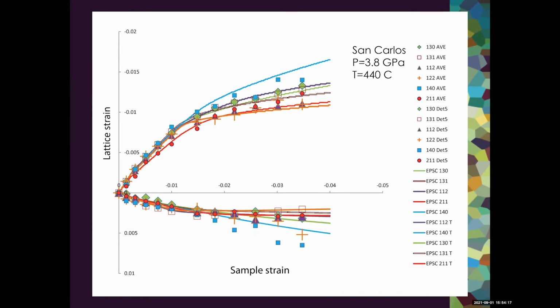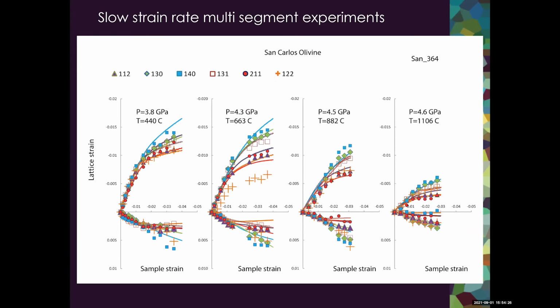Then as we add in the slip systems of olivine and kink banding, we're now able to get those curves to flatten out and overlay the data much nicer. So here are the EPSC models for all 4 experiments that I showed earlier, and we can now see that we're able to match the early diffraction data as we increase in temperature.